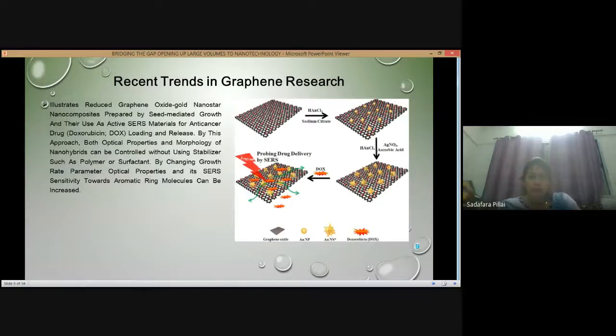And in the cancer field, when we add gold chloride, silver nitrate, and ascorbic acid to graphene, it is loaded with doxorubicin. Then by probing the drug delivery, it works as surface enhanced Raman spectroscopy, and drug release happens. So it works as a stabilizer, polymer or surfactant, and by changing growth rate parameters and optical properties, its surface enhanced sensitivity towards aromatic ring molecules can be increased.